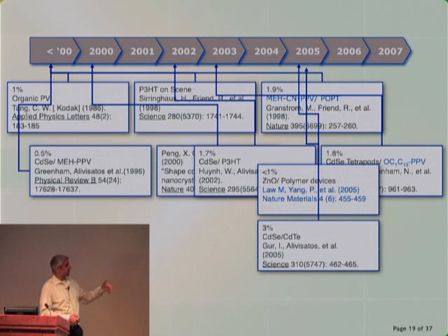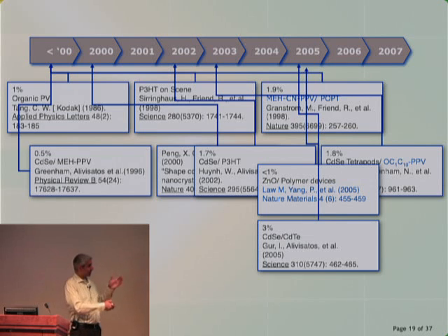So more recently, these hybrid devices were combined with nanowires, but another thread that actually occurred again in our lab was an all-inorganic nanoparticle solar cell. So basically we said, forget the polymer altogether, that's become a limit. Why don't we take all the polymer out and just use nanoparticles? And my colleague Alon was working with CdSe and CdTe.